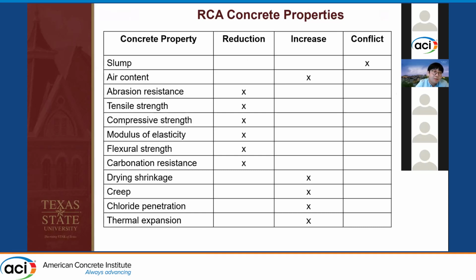We know lots of researchers and scholars around the world did lots of lab tests. And we all know the addition of RCA into concrete could change concrete properties very significantly. Based on our literature review of the lab studies, here we summarize the effect of RCA on concrete properties. By adding RCA, the effect on slump can either be improved or decreased, so it really depends on the mix design and also RCA quality. And by adding RCA, we are likely to have higher air content in the new RCA concrete. The concrete abrasion resistance, tensile strength, compressive strength, MOE, flexural strength, and carbonation resistance will be decreased. And the drying shrinkage, creep, chloride penetration, and thermal expansion will be increased by using RCA.